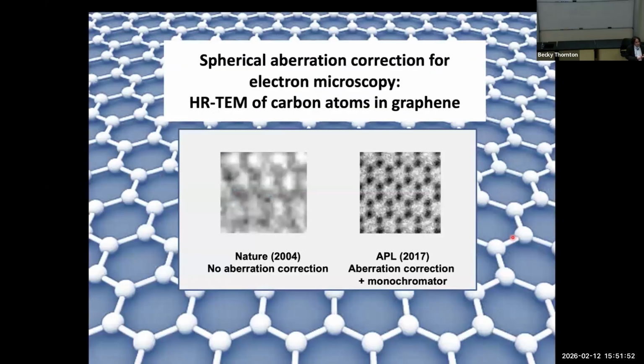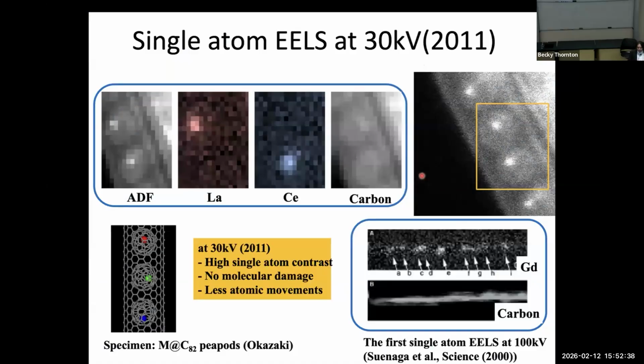Then we use this microscope to get information from carbon materials. This is the comparison of our own images. In 2004, we didn't have any aberration correction, so we could barely see the hexagonal alignment of the carbon materials. But once you get an aberration corrector and a monochromator to reduce the chromatic aberrations, you can very clearly see each carbon atom. This is a big advance for a long time. Then I come back to the spectroscopy.